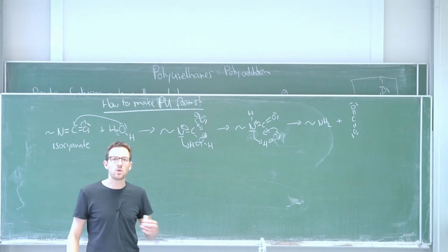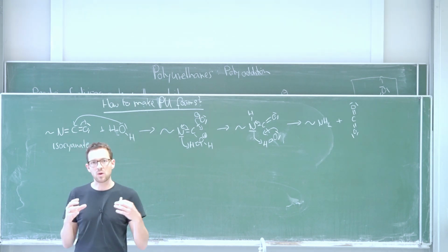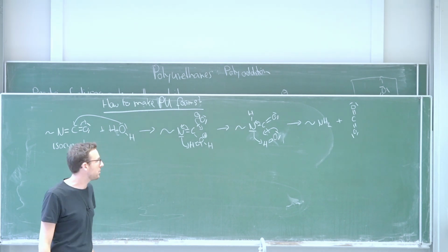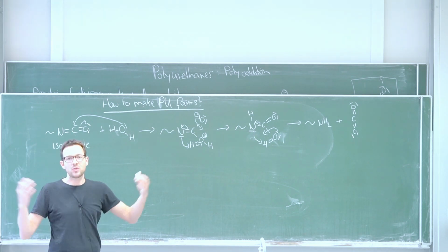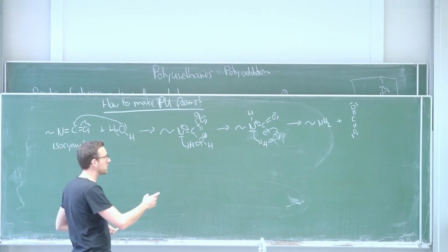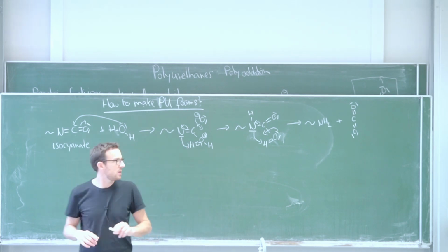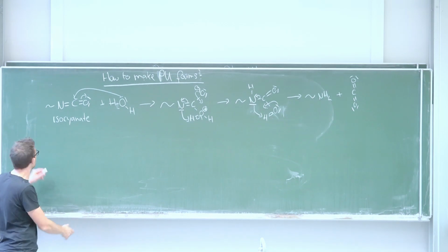Okay, this is the trick of the polyurethane chemistry. In your bottle, you have very small polymers so that they still remain mobile and liquid. These polymers are made in a way that they contain isocyanate groups at the outside. Then, while it sprays out, they undergo a reaction with water, start to foam, so you foam up the polymer. And now the last trick, the amine can continue to react.